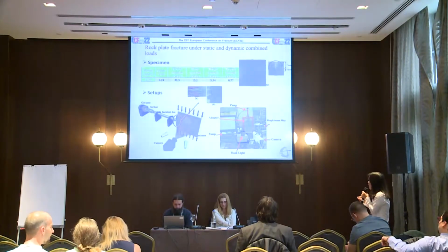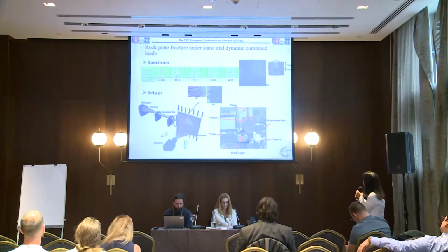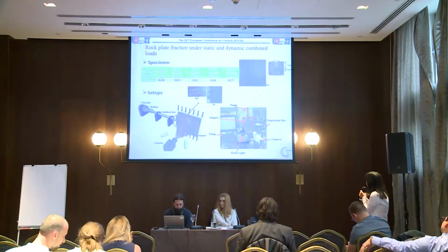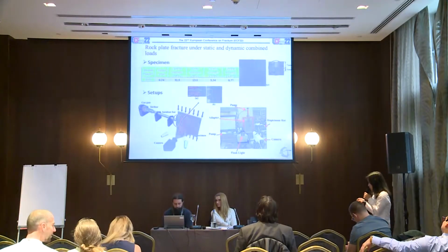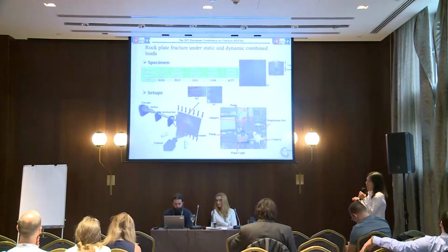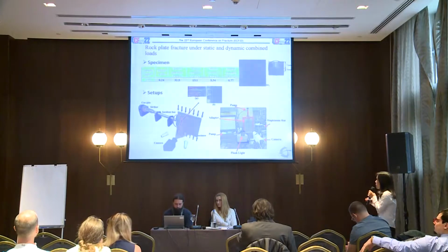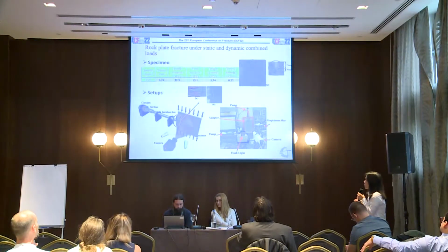The static compression load was exerted by a hydraulic pump with an adapter here. The dynamic fracture process was recorded by an ultra-high-speed camera with a frame rate of 50,000 frames per second.